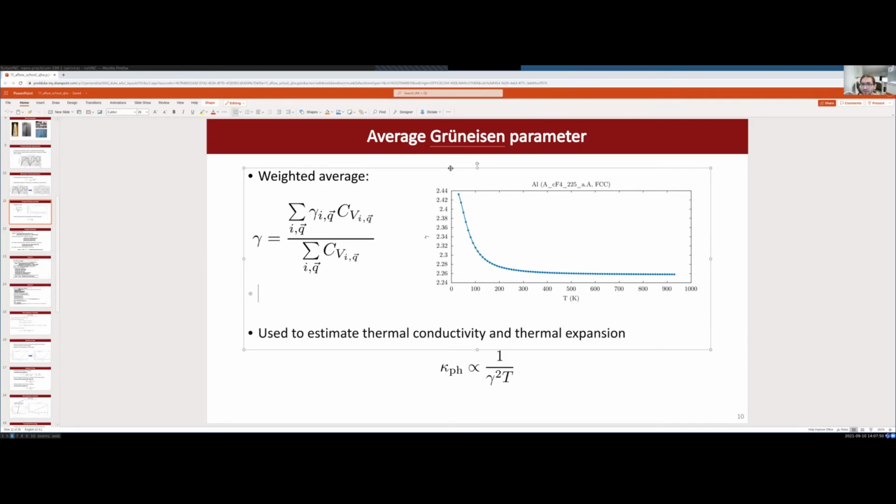Since heat capacity at 0 is also 0, here you start getting a divergency like 0/0, right? And it might lead you to wrong impressions that there is a peak. But it actually will have some finite value. Unfortunately, we cannot really resolve it in our approach.